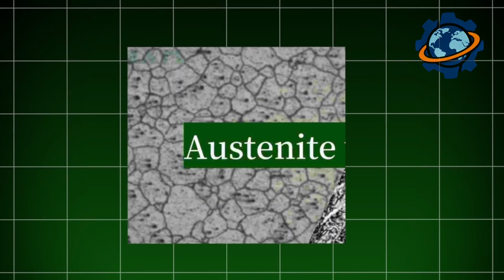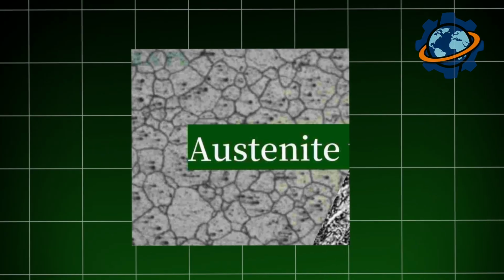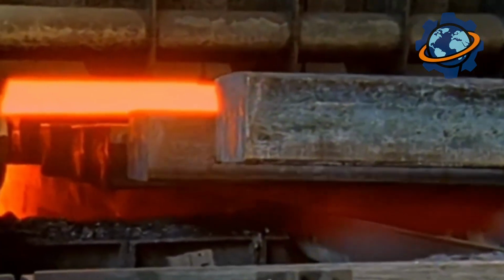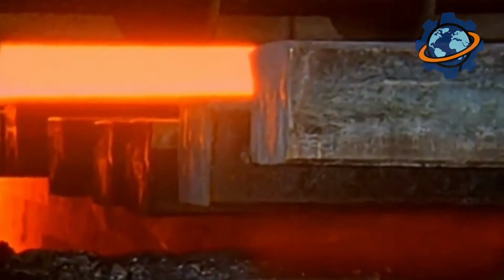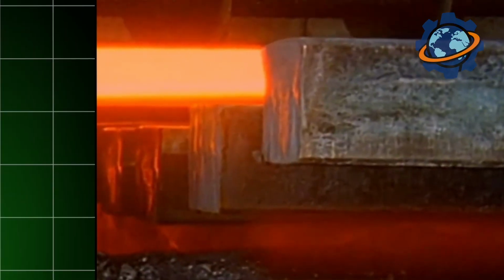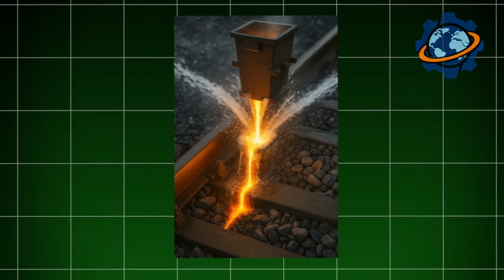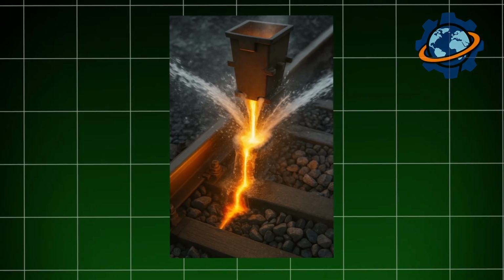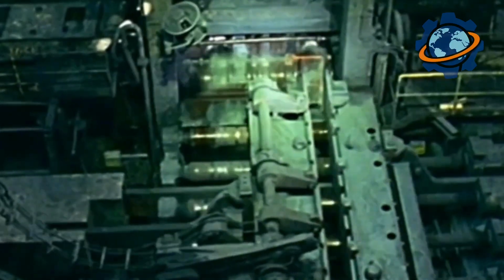But the main event starts after that. The rail is instantly cooled. Jets of high-pressure water are aimed along the head and web, the very parts the wheel rolls on. The temperature drops in a flash, and a new structure forms in the metal, martensite, an extremely hard, wear-resistant phase.